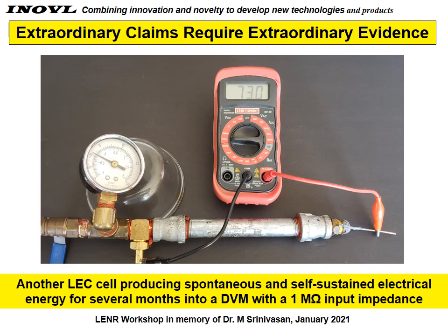Here's another LEC. The difference being in this one that we used a galvanized pipe instead of a brass pipe. The primary reason for doing that is galvanized pipe or zinc has a different work function than brass. For this test, you see that we were producing 73 millivolts through a 1 megohm impedance, and the pressure in the cell in this case was about -8 inches of mercury, and it has also been operating for several months.